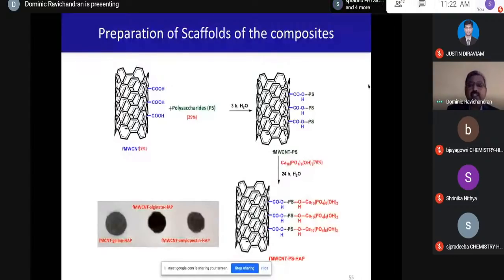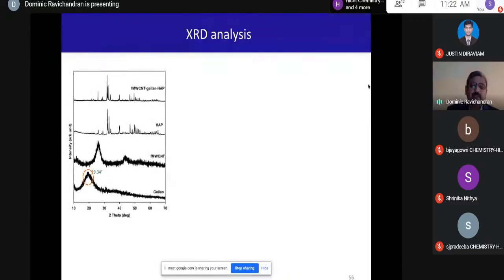In the characterization part, we use XRD analysis, where we record the XRD of the polysaccharide, which gives a peak at 19.34, and that of the functionalized multi-walled carbon nanotubes, which is seen at 26.05, and the HAP and the composites. The polysaccharide is amorphous in nature, and HAP is crystalline. The functionalized multi-walled carbon nanotubes are predominant.